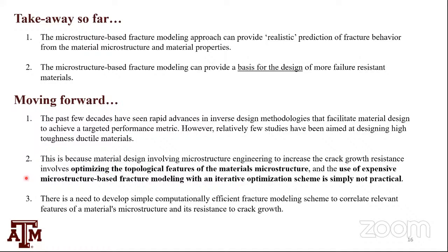So we cannot really use these things that I've shown so far, microstructure-based fracture modeling, with any of these optimization schemes, which are generally iterative, to design a material with enhanced fracture toughness. It just becomes unrealistic. So there is a need to develop a computationally efficient fracture modeling scheme to correlate material microstructure and its crack growth resistance, so that one could really use it in designing. And also these microstructure-based calculations are limited to people who have optimized codes and access to good computational resources.